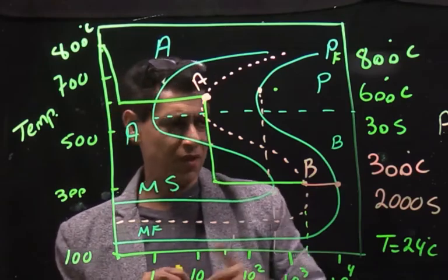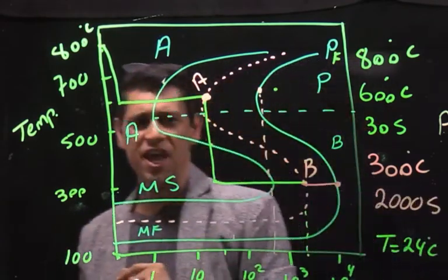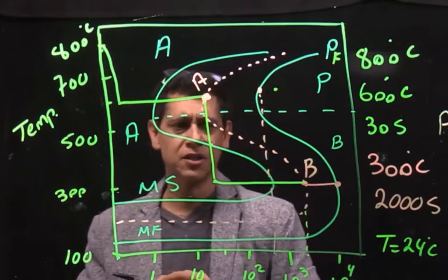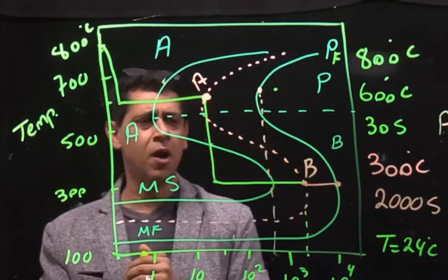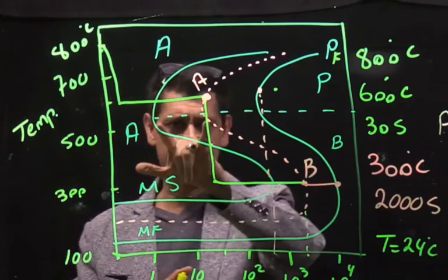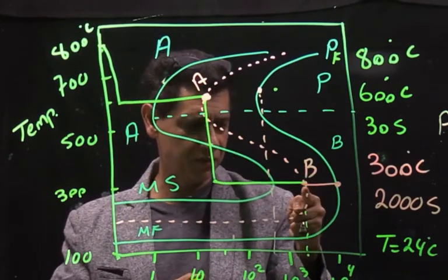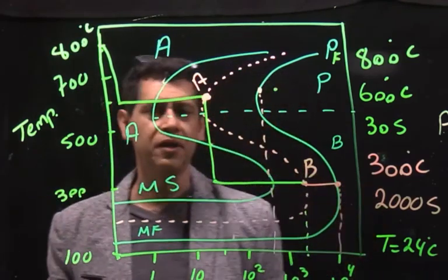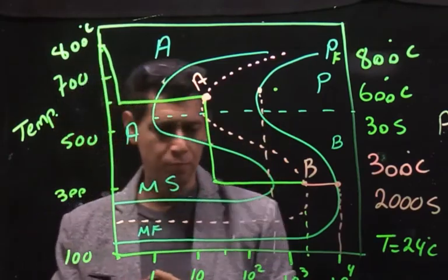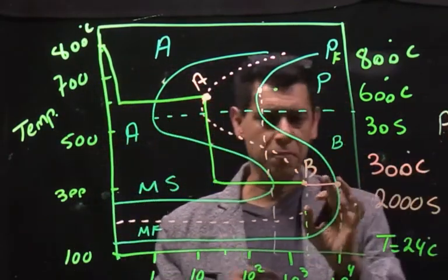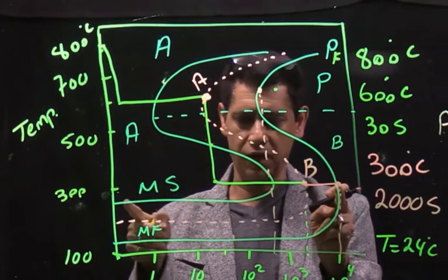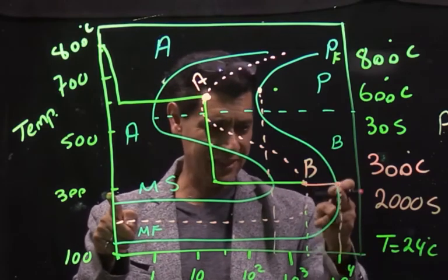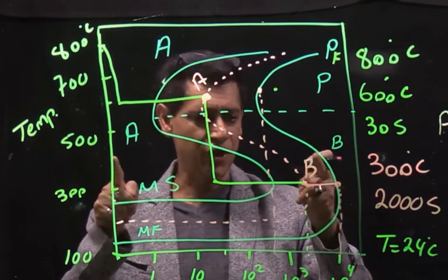bainite. If I had asked how long it takes to prevent getting martensite in this situation, so you have 50% here, you go further. Your answer would be, look at that now, you want to finish all the unstable austenite to bainite, so you have 50% austenite here, but it doesn't matter, it takes this long, and that's 10,000 seconds, so you need 10,000 seconds.